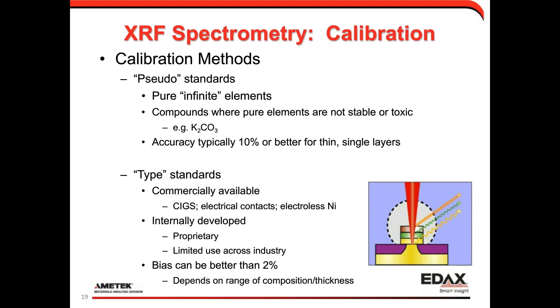Typically, accuracy in these sorts of methods is about 10% or better for thin single layers. You can also get type standards which are matched to your system. You can buy these commercially. If it's something proprietary, they're typically internally developed. EDAX is also available to work with customers and various vendors to have standards made as well.